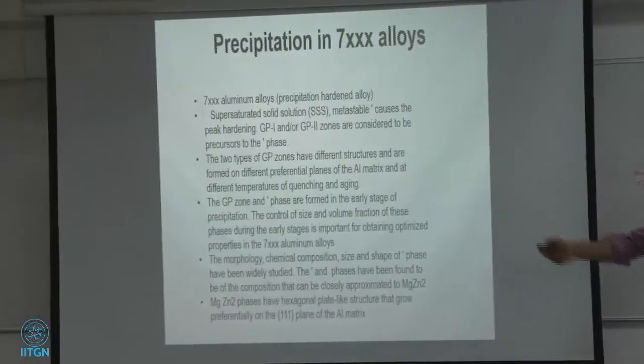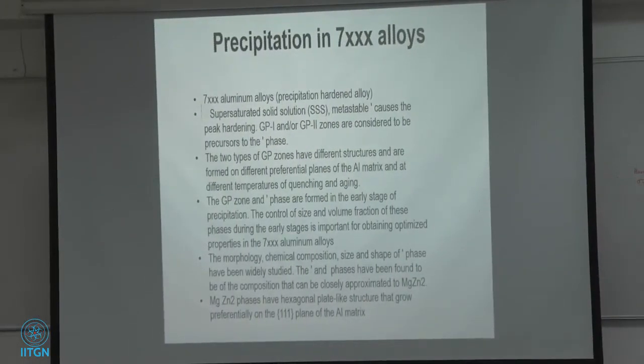So here, just before here, the GP zones come out. GP1 and GP2. These are Guinier-Preston zones. They're really not precipitates, but they're a collection of atoms. Maybe 15 atoms, 20 atoms collection, okay? They're forming the nucleus for the precipitate next. Are considered to be precursors to the eta prime phase. Okay, this is all fine. Size and volume fraction changes, fine. That's all fine. This is the eta prime.